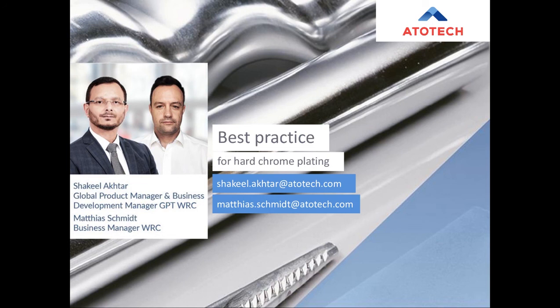In terms of corrosion protection, there are various factors which influence these particular properties. The most important factors are that we need to make sure that the substrate we are plating the chrome layer on top of is completely defect-free. So any defects on the substrate will have negative effects on corrosion resistance. Most applications for hard chrome deposits in terms of corrosion protection will depend on the environment that the parts are subjected to, and also the pre-grinding and post-finishing operations after plating.